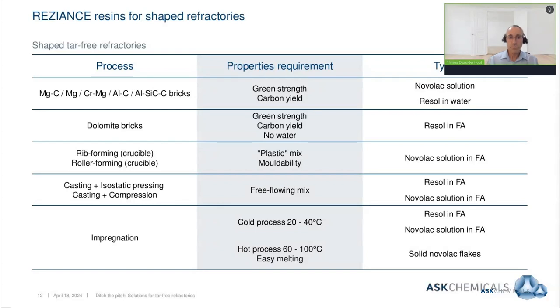Or let's refer rather even to a cold crushing strength or compression strength that you're looking for in the end. In the case of dolomite bricks, where you cannot tolerate the presence of any water, we would rather prefer to use a resol in furfural alcohol. Of course, not even considering a water-based resol, but in this case, a resol in furfural alcohol with moisture content levels less than 1%.